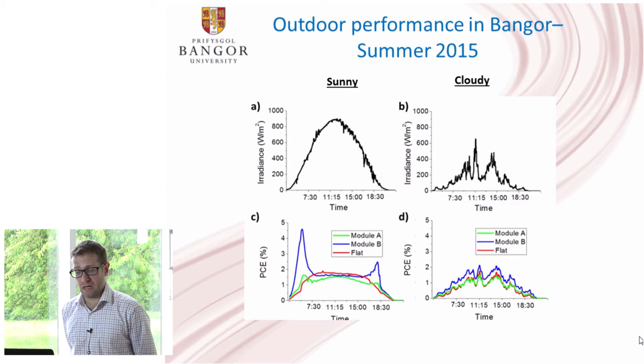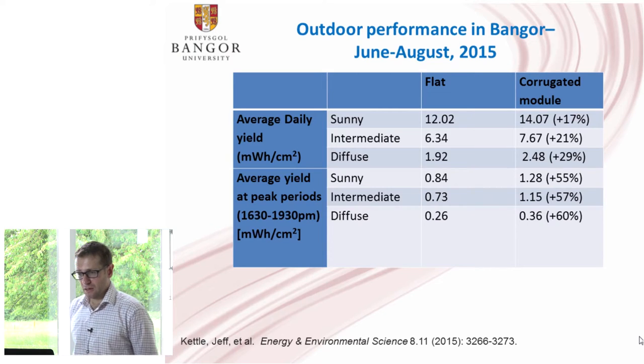So under cloudy conditions, we have a lot of diffuse irradiation, and it's very difficult to pick out any specific trends from our cloudy data. However, what we tend to do is aggregate that data over the course of a number of months. So we did around about 3 or 4 months of testing, and then we looked at the average daily yield of each type of module. And what we find is that the three-dimensional module, so the corrugated module, gives a bigger energy yield. So on a sunny day, what we tend to see is around about a 17% increase in the efficiency. And then what we find is as it becomes more and more cloudy, then we get a bigger and bigger increase in the energy yield.